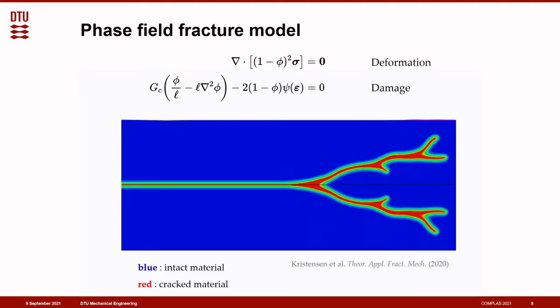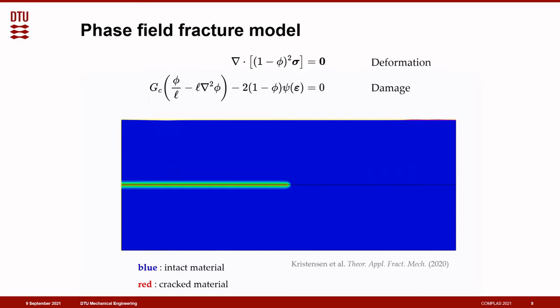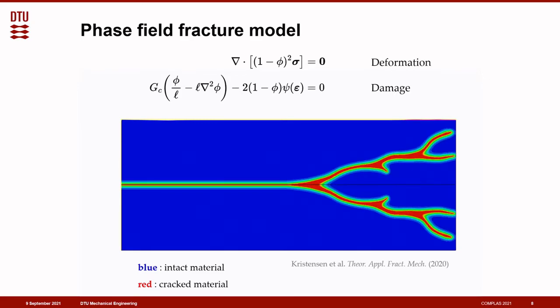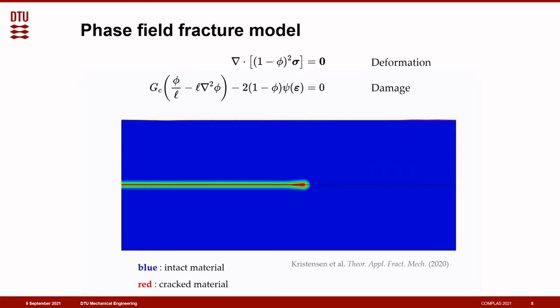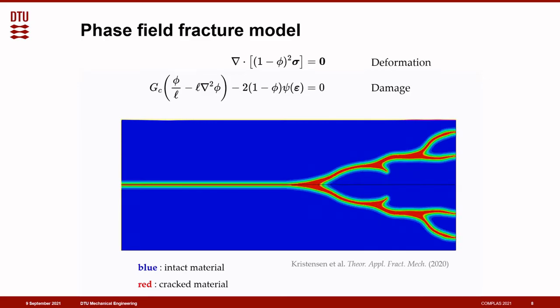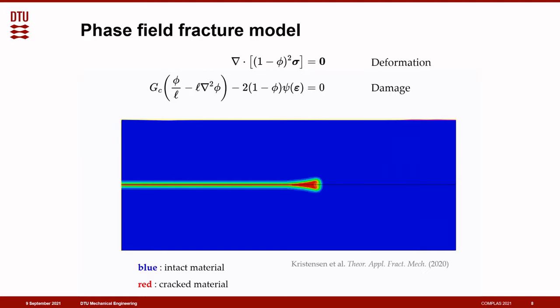You can get a good overview by looking at these two balance equations. The first equation is the solution to the deformation problem. Basically, the standard balance of linear momentum with the phase field degrading the stiffness of the solid. And the second equation is the phase field evolution, which is basically a competition between the strain energy density stored in the solid and the toughness of the material.